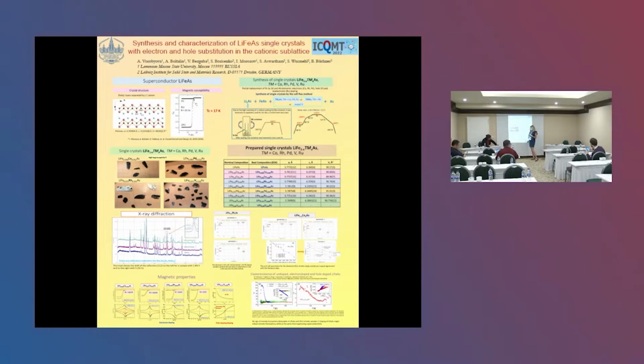Here we can see the magnetic measurements of these crystals. With increasing substitution of iron atoms, we see a decrease of the critical temperature of the superconducting transition. But if we make hole doping with vanadium, there is no superconductivity at all. Only in this compound can we see the nematic fluctuations that we do not see in other doped crystals. So I think that's all. Thank you.